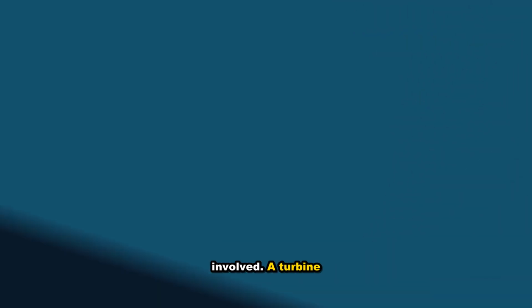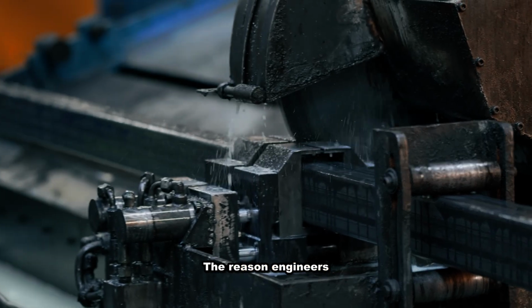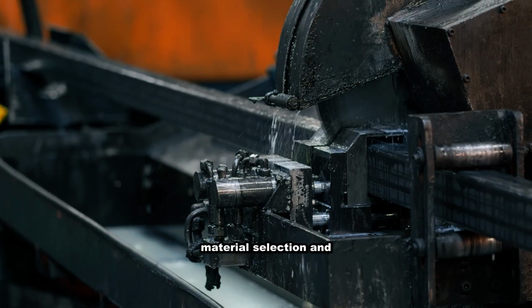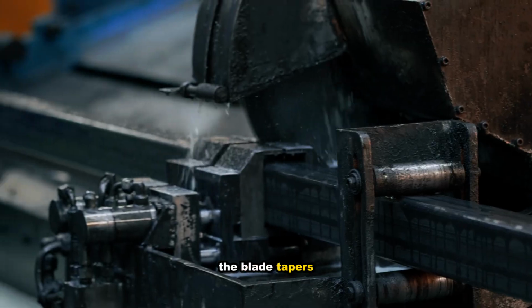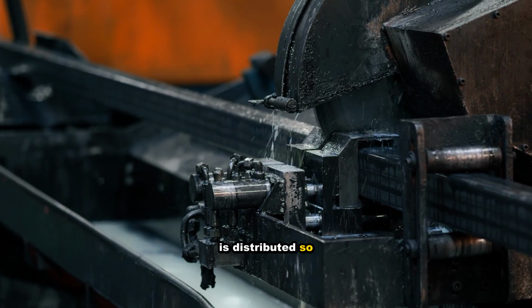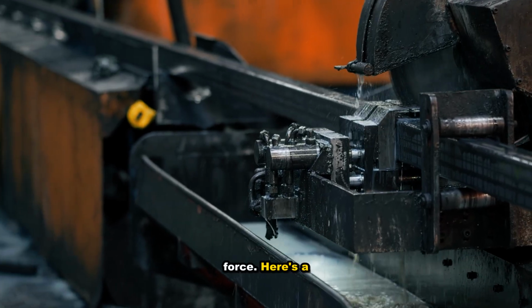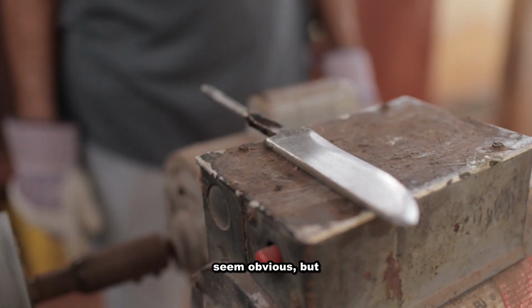Now let's talk about the forces involved. A turbine blade experiences centrifugal acceleration of about 50,000 times Earth's gravity. Imagine a blade that weighs 100 grams. The centrifugal force pulling on it is equivalent to 5,000 kilograms of weight trying to rip it off the rotor. The blade is attached at the root, which is the thickest part. The root has to be strong enough to hold the blade against that force while also being aerodynamically shaped so it doesn't create turbulence. The reason engineers can make this work is through material selection and stress distribution. The root is thicker, the blade tapers toward the tip, and the stress is distributed so no single point experiences the full force.